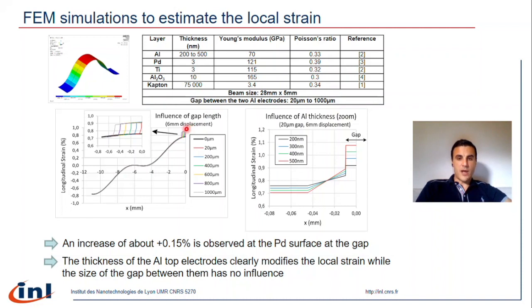The gap is here at the position 0. From this graph, we could learn that there is an increase of the local strain within the gap, an increase of 0.15% strain. These results explain why the cracks are preferentially formed within the gap. The strain is indeed higher within the gap than outside the gap.